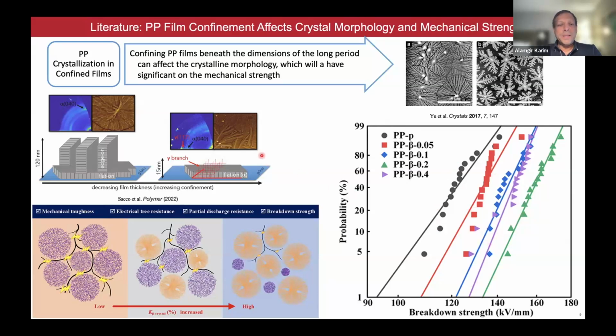In thin films, people have speculated on crystal orientation effects, flat-on, edge-on. If you get ultra thin, including in our own work, we have shown that you go from spherulites that impinge on each other to something like dendrites. And the general idea is that morphology, controlling the lamella orientation, etc., could be important.